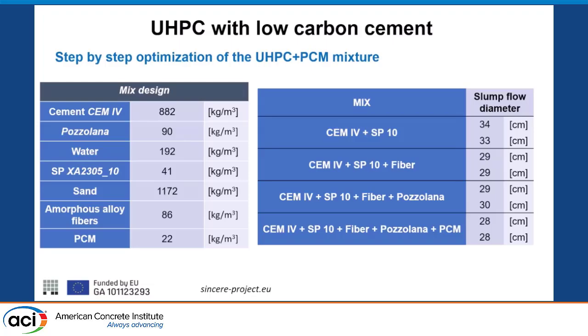So we ended up with this, and you can see here we started only with the cement, and then we added the fibers, and then we added the pozzolana, and finally we ended up in the final formulation also with some phase-changing materials. Because if we want to use this as a retrofitting, not of an artifact like this, but think of a wall panel, you can also ask your retrofitting to perform some kind of energy retrofitting task to improve the thermal insulation, especially in hot climates. You want to keep it cool during summer and avoid being overheated. So you can see that starting from this first target, which was what we obtained, we decreased a little bit, especially by adding the fibers, but we still had a good flowable mix.